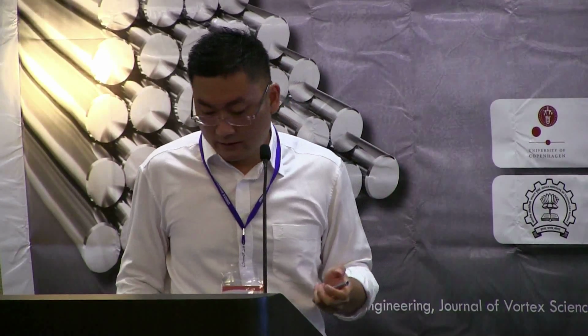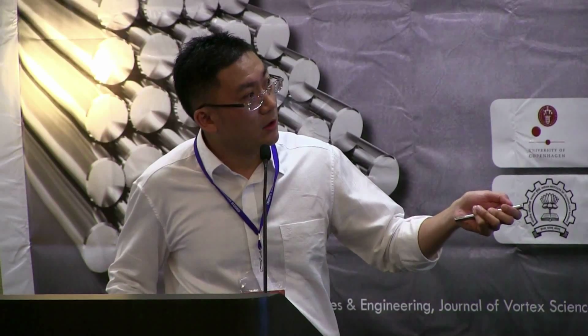So that's why we change different molar ratios, and we finally find that with more platinum in the molar ratio, the nanoparticle size will be much smaller because we have less precursor concentration here, and we can control the particle size, which is very important for the performance. So from here you can see this is 1 to 1 molar ratio, 2 to 1, and 3 to 1, and maybe not very good at SEM. So roughly we can see the distribution of nanoparticle is getting smaller. So if you look at the comparison, you can see the range from 250 to 1 micron to 800 nanometer and 1.7 micron. And then this is the mean diameter of the nanoparticle.